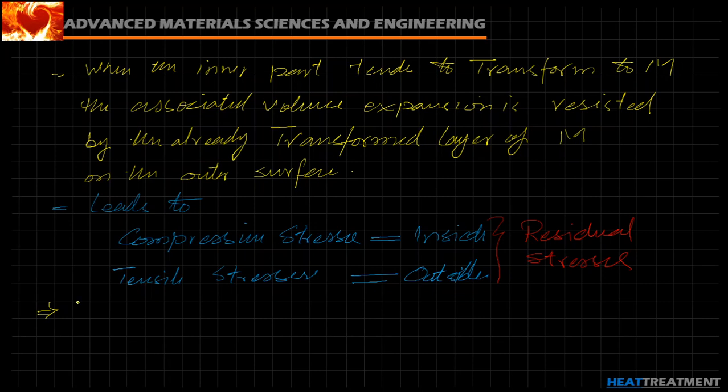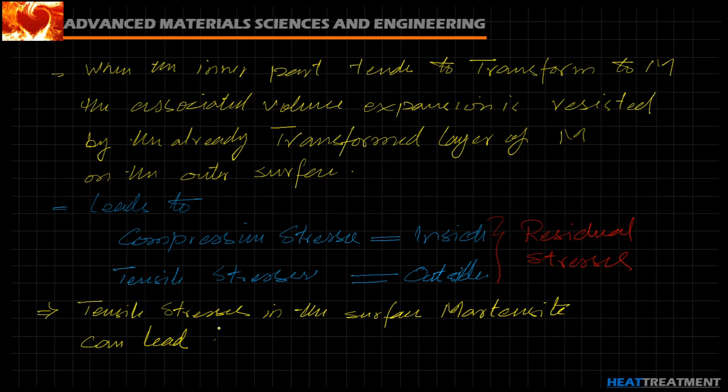So we can say the tensile stresses or formation of tensile stresses in the surface martensite can lead to cracks known as or called quench cracks.